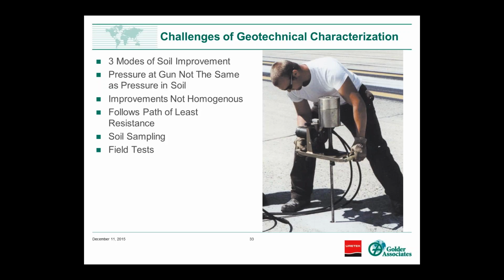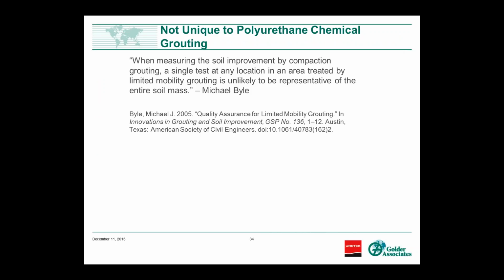The polyurethane follows that path of least resistance, so it's not a very uniform improvement in a lot of cases, particularly when you're looking at that lattice type of structure. So with that in mind, the field tests, and this is a picture of someone running a dynamic cone penetrometer, and even if you were to excavate and grab samples, it's really challenging to get good representative samples that will tell you what's going on. But I did want to point out that this is not something that's just unique to polyurethane grouting. Pretty much almost all types of grouting have this issue. It's a real challenge. I certainly don't have all the answers here, but I think it's something that will continue to be a challenge for our geotechnical engineers like me. But it's something that we're definitely giving a lot of consideration.